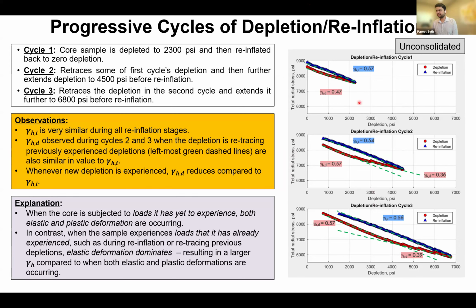So what are the key observations from this experiment with progressive cycles of depletion and reinflation? The first one, which is very interesting, is that the reservoir stress path coefficient, or the injection coefficient, in all of these cases is very similar. So 0.57, 0.54, 0.57. One could say it's around 0.55, 0.56 on average. Very, very similar, right?